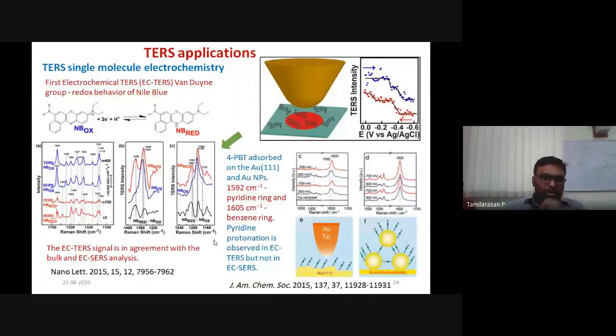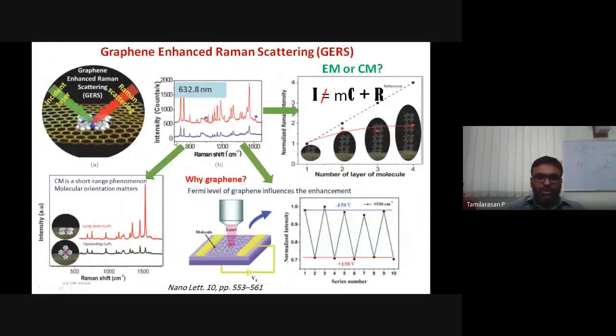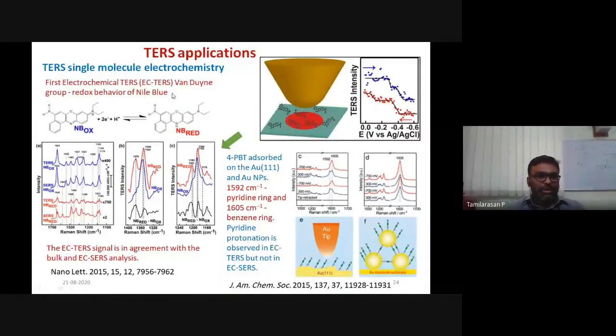Another application here is once again done by Professor Van Duyne, who invented SERS effect. Here, what they have done is they took Nile blue in oxidized and reduced form. In oxidized and reduced form, Nile blue gives you two different spectra, as we have seen in hydroxylated PEDOT. So they have tested this with both TERS and SERS. Okay? So in TERS and SERS, you will see clearly almost a similar spectrum for the oxidized form, but while you reduce, there is some difference that I'll discuss here.